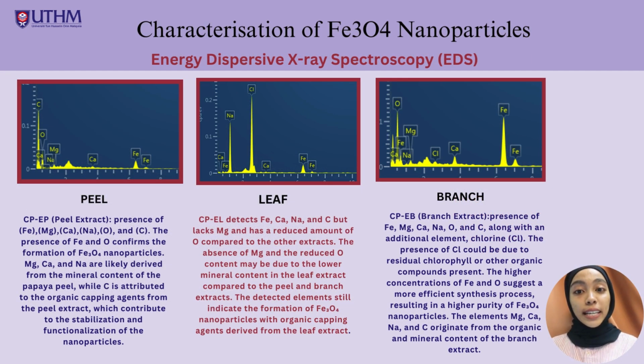The last characterization of iron nanoparticle, which is EDS, that shows all the elements in a sample. So the first sample, which is peel extract, presents iron, magnesium, calcium, sodium, oxygen, and carbon. The presence of iron and oxygen confirms the formation of iron oxide. Magnesium, calcium, and sodium are likely derived from the mineral content of the papaya peel, while carbon is attributed to the organic capping agent from the peel extract.